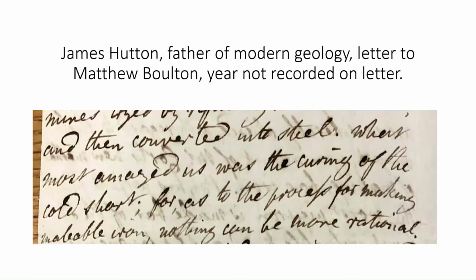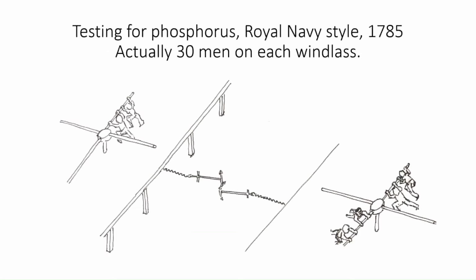The Navy ran a sort of special test comparing an anchor made with Swedish iron against one made with Henry Cort's iron. And Henry Cort's product actually came out better than Swedish on something like 60% of the occasions. I think they ran 5 tests. So, you know, clearly it was very good, but it had technical problems to begin with.